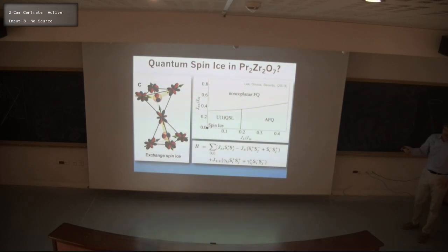and so it can describe the quantum fluctuations associated with the spin ice state. This is completely different from something like dysprosium titanate, because there the Ising spin is actually a plus minus J state. So it's really as aligned along the z-axis as it can be, or anti-aligned. So it's basically got these two states in the low energy crystal field manifold.